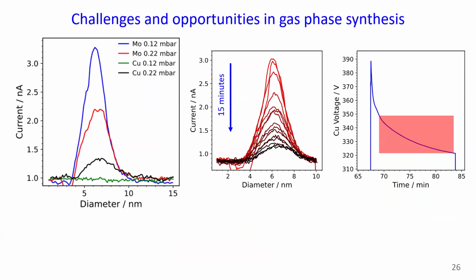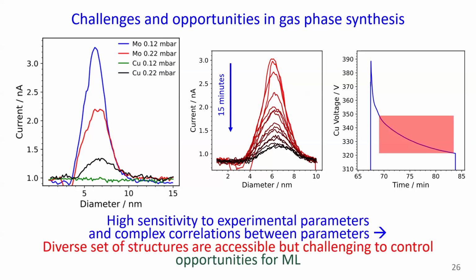Exactly. And so, for example, here you can see this is the current through the mass spec. So this is essentially the particle yield rate or your deposition rate. And so you can see going moly versus copper under the same conditions, you have very different deposition rates. And so that is where employing machine learning to develop a model that can relate the parameters to the desired structure is something to pursue in future work. So yeah, high sensitivity to experimental parameters and complex correlations between them, which is good because we can access a diverse set of structures, but it's also challenging to control, and so opportunities for the expertise of everyone here.